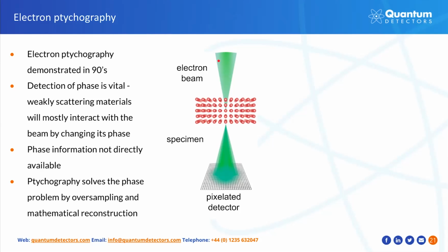I'll give a short explanation of what the phase is and why we would like to detect it. The beam at the specimen can be described by complex functions. They have real and imaginary parts. When the beam interacts with the specimen, its magnitude and phase are altered. Unfortunately, when the beam eventually gets detected, the phase information is not directly available at the detector, and this leads to a loss of important information. For example, very weakly scattering samples, like very thin 2D materials or biological specimens, mostly interact with the electron beam by altering its phase, so this information is lost.